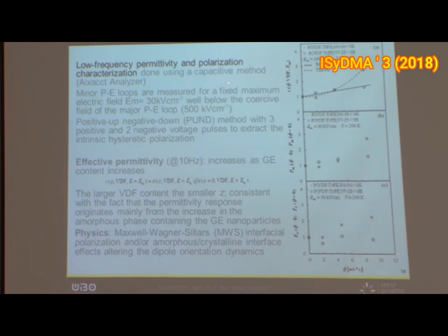Basically, we use a capacitive method to measure the minor loops of the system, but we also use another method called the PUND method, because when you put some conductive particles in the system, you have to be very, very careful about the conclusions and results you get, because it affects the minor loop system. So the PUND method relies on the use of positive and negative voltage pulses, and if you get the same result with the two methods, your conclusion can be very carefully understood.